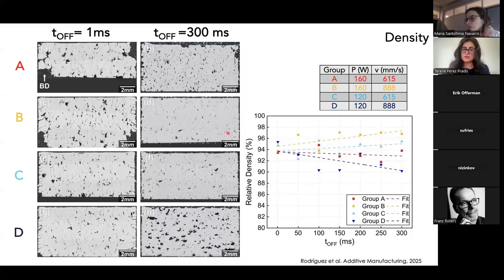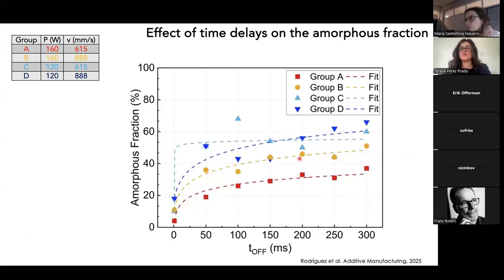But for some conditions, it seems the introduction of time delays not only doesn't hurt the density, but it can even allow a higher density. Let us see how we are doing in terms of amorphous fraction. This is key for our study, and this is what this plot shows. Amorphous fraction versus the time delay. So for all the groups, again, with the same color coding.